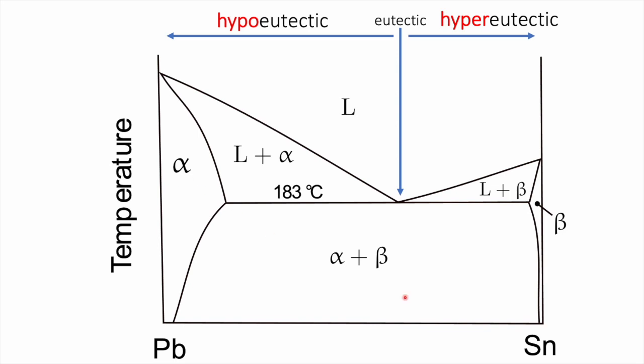So the reason why pewter was made of a particular lead-tin alloy which had a eutectic composition is simply that you get to a very low melting temperature of 183 degrees centigrade.